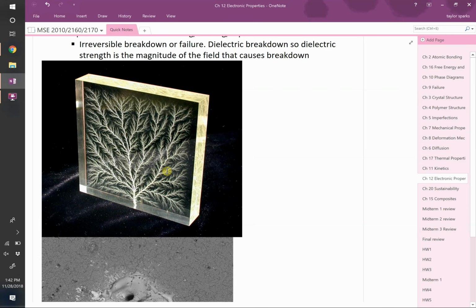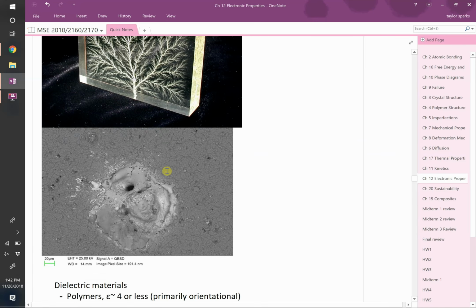So now a whole bunch of electrons start moving very quickly, and that causes localized Joule heating, which melts your material. It completely destroys your material. So even materials like ceramics, which you'd think don't melt until 3,000 degrees Celsius, if you put a large enough electric field on a spot, it looks like it's melted because it did melt. So dielectric breakdown leads to pinhole failures, where locally melted is really what's happening. All materials have a fundamental limit, which we call the dielectric breakdown, which is some electric field, and if you go above it, you will get lightning. You'll get current massively traveling in one local spot, which will melt your material. So the bummer here is you can't just keep increasing voltage, because you'll reach a limit where you have dielectric breakdown.